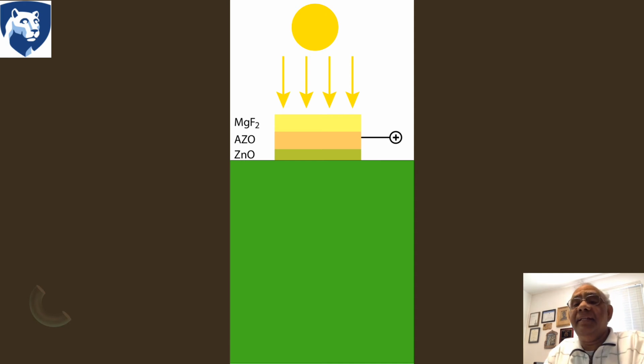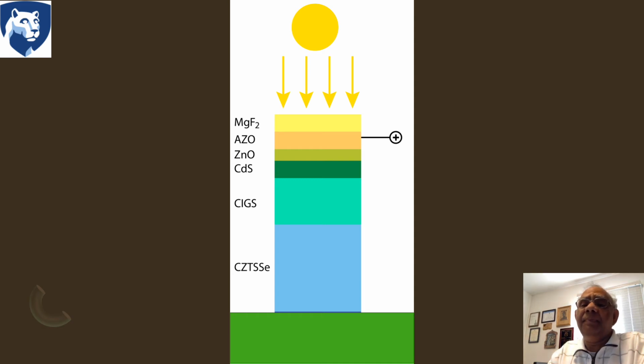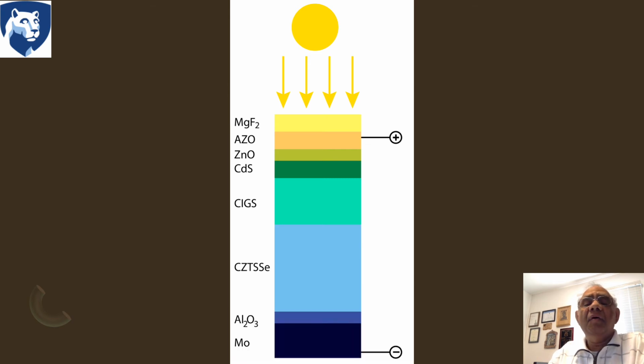This solar cell has a magnesium fluoride anti-reflection coating, an aluminum doped zinc oxide front contact, and an oxygen deficient zinc oxide front passivation layer. Then come an N-type cadmium sulfide layer, a P-type CIGS layer, and a P-type CZTSSe layer. These are the three main semiconductor layers, followed by an aluminum oxide back passivation layer and a molybdenum back contact. Note, there is only one NP junction, but the semiconductor structure is of the NPP type.